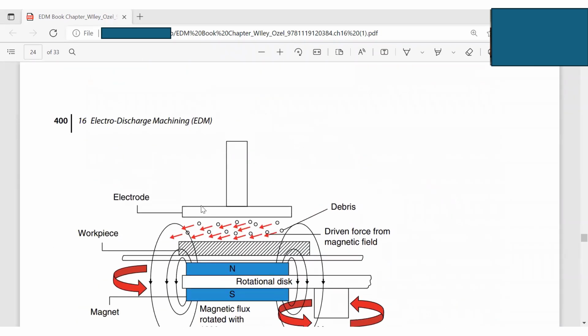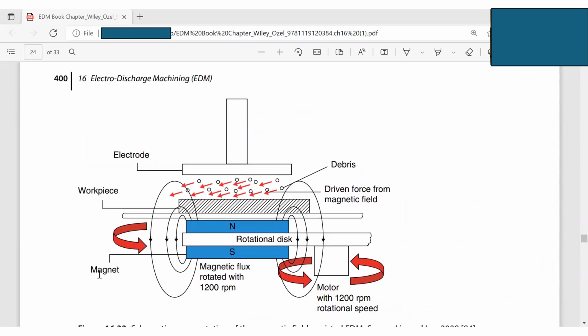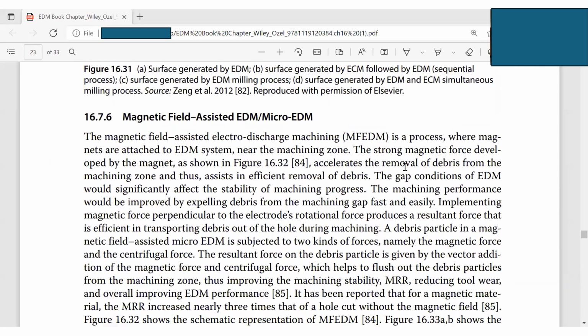So here this is an electrode, here is a workpiece, and we have a magnet here. Here is polar N and polar S. So we have two polars, N and S. The magnetic flux is rotating. This guy is rotating at 1,200 RPM, a rotational disk. So this is the debris. You can see the debris is driven by the force from the magnetic field. This accelerates the removal of debris from the machining zone and thus assists in efficient removal of debris. So this is higher efficiency.